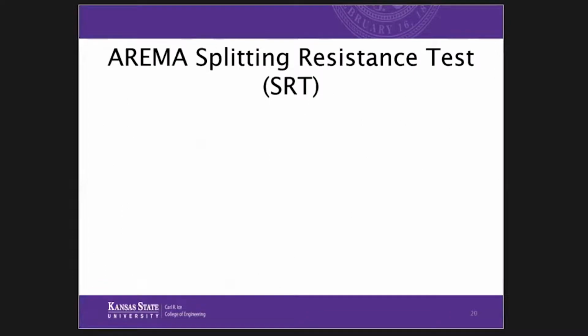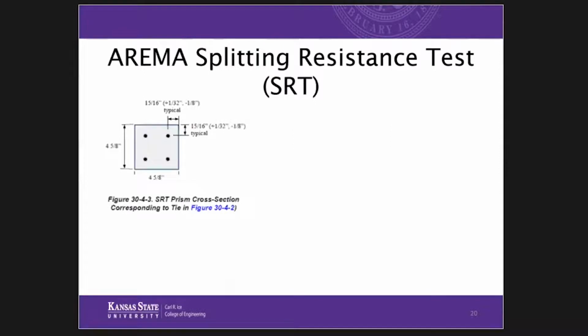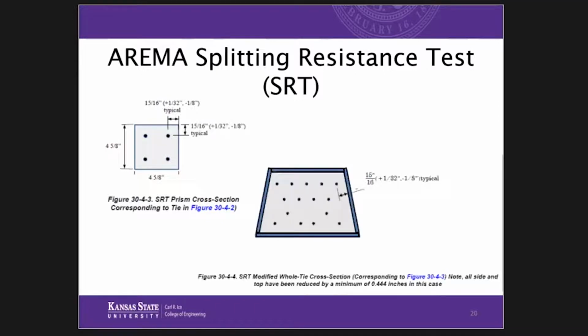The other test that we developed, a system test, is the AREMA splitting resistance test, and Riley showed a picture of this as well. If we have a tie design that we want to use, that tie design will have a concrete mixture and a release strength and a wire type. We can see, are we at risk of splitting by using the AREMA splitting resistance test? What that does is, for our tie that we want to use, we reduce the edge distance of our reinforcement, from the center of the reinforcement to the edge. We reduce that distance by 25% and make 6 members.